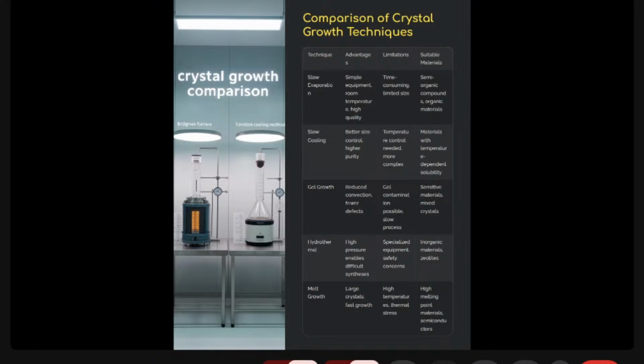Now there are various methods for growing crystals. Let us begin with slow evaporation. It is a classic and widely used technique, especially in the domain of semi-organic crystals as well as organic crystals. In this method, the solution containing the desired compound is left undisturbed. We make a solution and keep it undisturbed for a longer period of time at room temperature, and over time the solvent evaporates slowly, leading to a supersaturated solution and subsequent crystal formation.